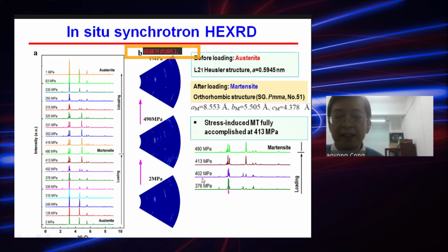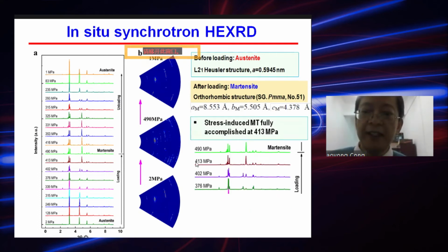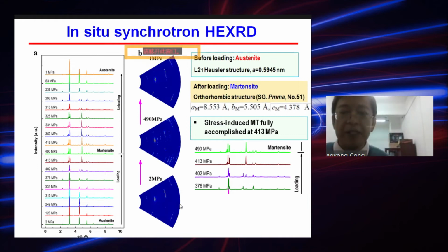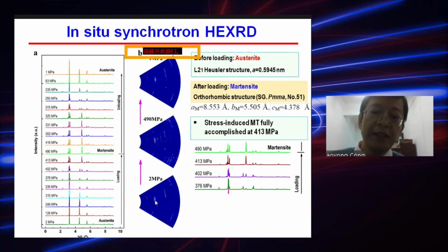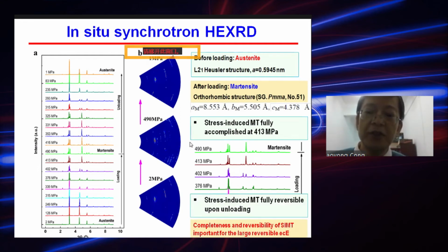We carefully analyze the X-ray diffraction patterns. We find that at 413 megapascal, the stress-induced martensite is complete with no residual austenite. We checked the two-dimensional diffraction patterns before loading, at the maximum stress, and after unloading. We find that the diffraction patterns before loading and after unloading are almost identical. This shows that the stress-induced martensite transformation is fully reversible.